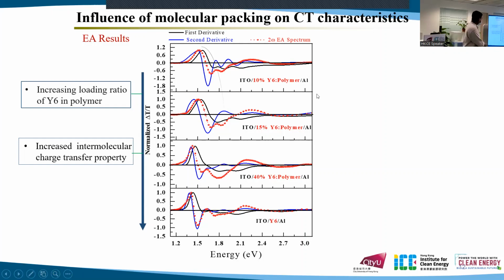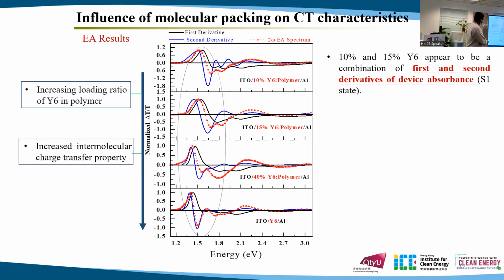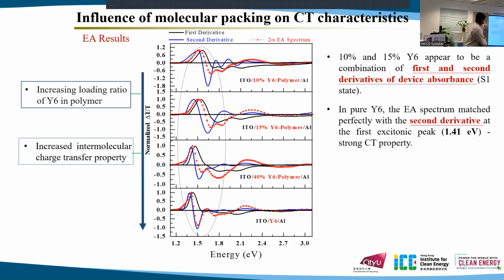And we are more concentrated on the S1 state because the S1 state is more responsible for the charge transfer and the exciton dissociation and recombination losses. In 10% and 15% Y6, you can see this is a combination of first and second derivative, right? It is not completely first or second derivative. And when we increase the concentration of Y6, you can see it matches the second derivative more. In pure Y6, it is purely second derivative. We can see the negativity, it is more second derivative.